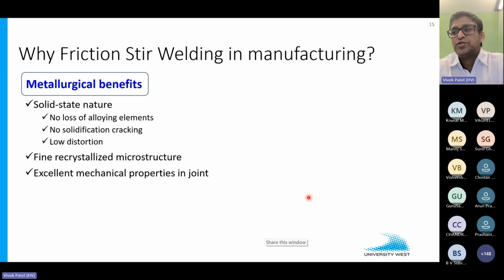Especially for those alloys having more than one element. In a fusion route, there is a significant chance that you will vaporize some of the alloying elements having the lower melting point. Here there is no loss. All the alloying elements are intact after the weld. There is no melting, so you get rid of solidification cracking. And due to the lower working temperature, you end up with minimum distortion.